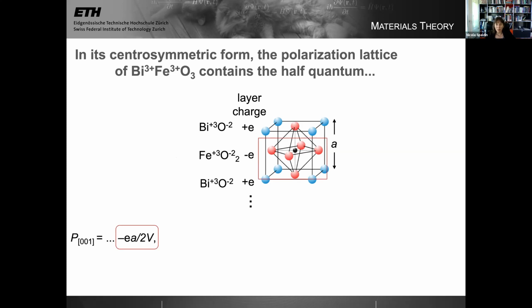So the polarization, if I work it out for this unit cell, I'm working out the polarization out of the plane in the Z direction. I have a charge of plus 1 at position 0. I have a charge of minus 1, so minus E, at position a over 2, where a is the unit cell, and I divide by the volume to normalize. If I took the blue square as my unit cell, I have a charge of minus 1 at position 0, so that contributes 0. Then I have a charge of plus E at plus a over 2, and I divide by volume to normalize, and so on. So I have this polarization lattice that contains the half polarization quantum but doesn't contain zero.